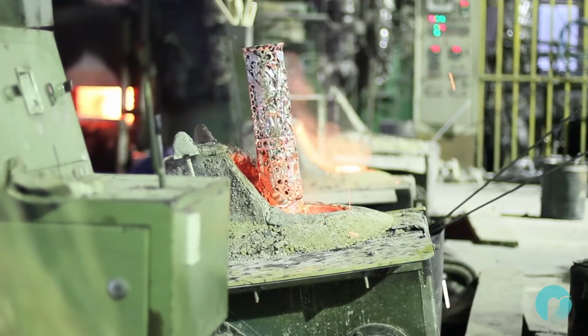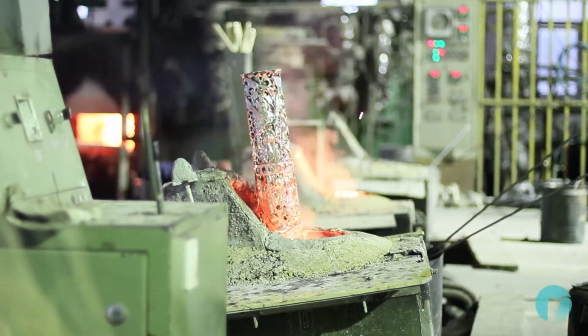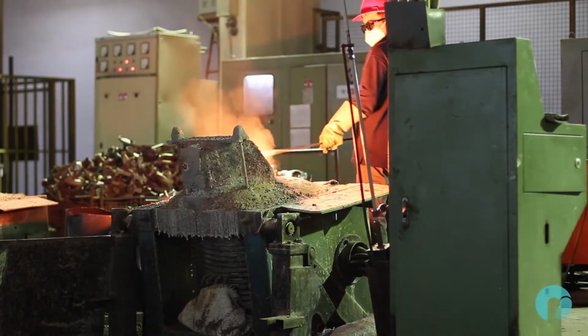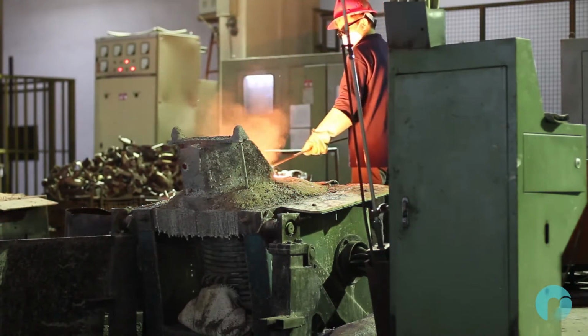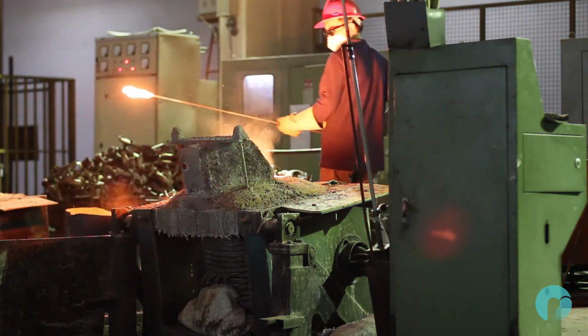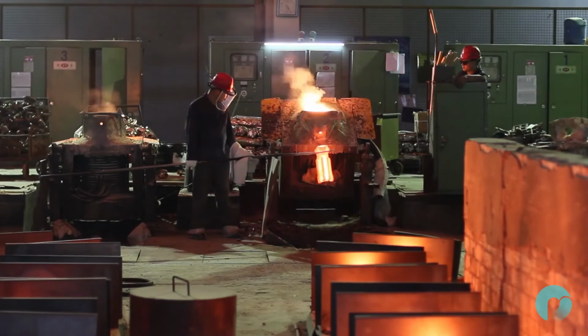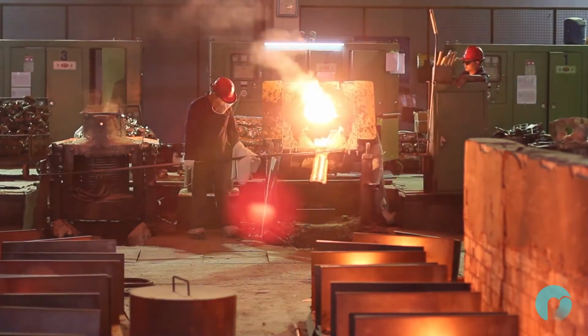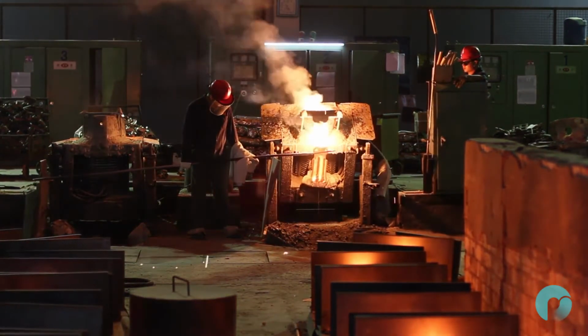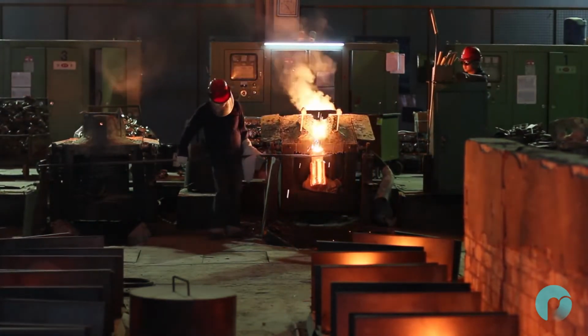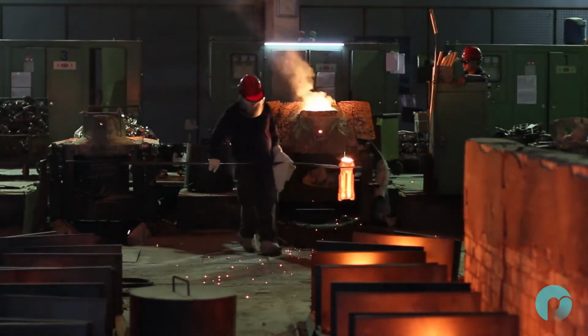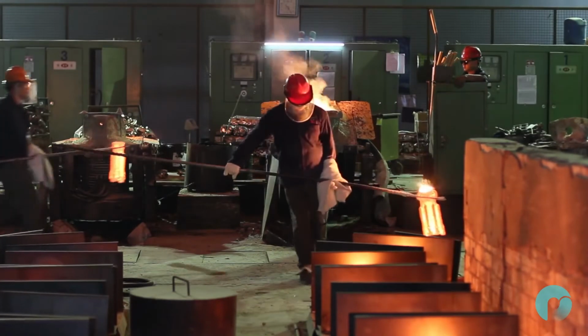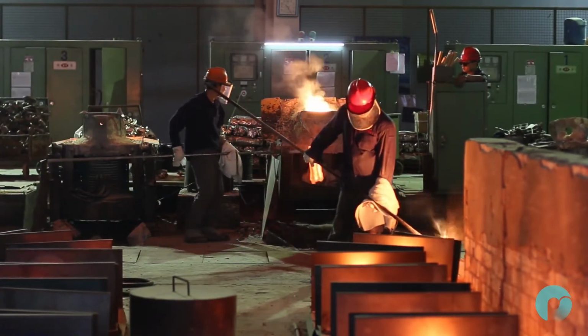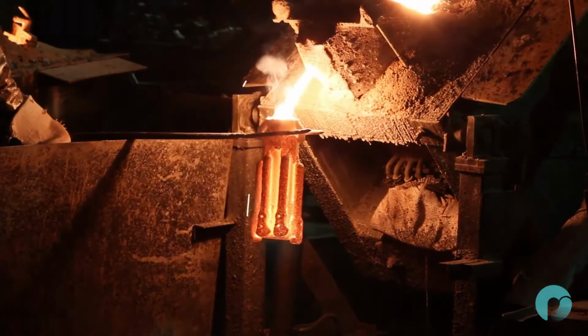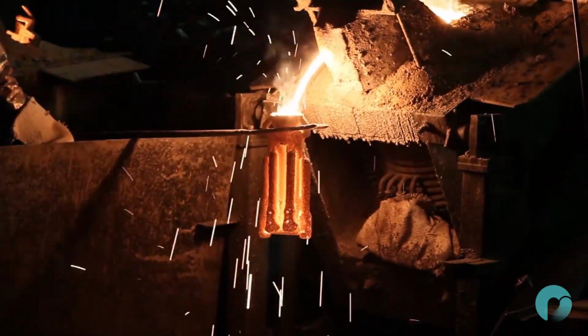The stainless steel is then melted using an electromagnetic induction furnace, which induces eddy currents within conductors by constantly changing the magnetic field. Eddy currents create heating effects to melt the metal internally, with no direct heat source, reducing the chance of contaminating the steel. Any scum and impurities are scraped off the surface and discarded. The stainless steel is heated to 1612 degrees Celsius, and the moulds are preheated to 1300 degrees Celsius.